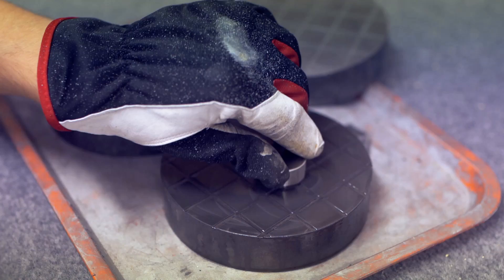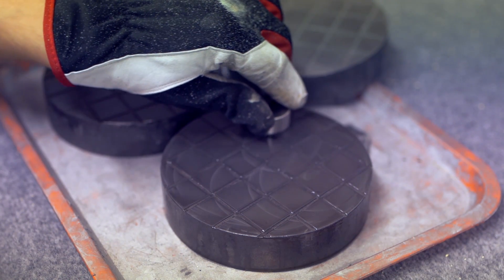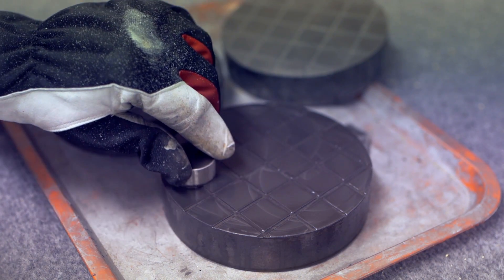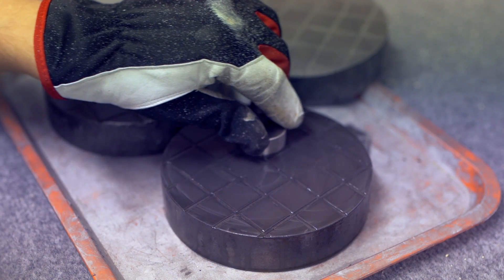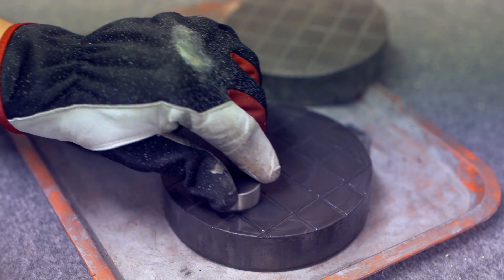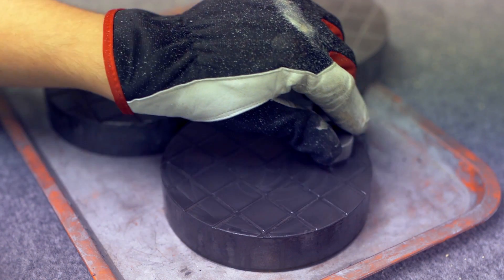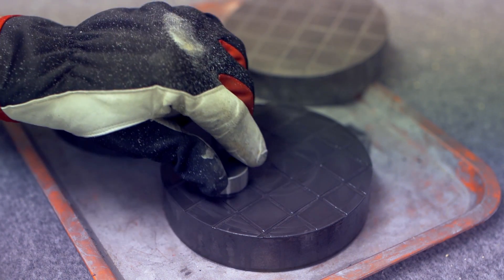But lapping soft metals is a real challenge. Copper, in particular. Not only is creating the plates a problem on its own, since relatively soft, non-embedding abrasives must be used. If, for example, a diamond compound is used, the risk is significant that a sharp piece of diamond will embed into one surface and shave off a chip from the other, creating a deep gouge and fouling the work.